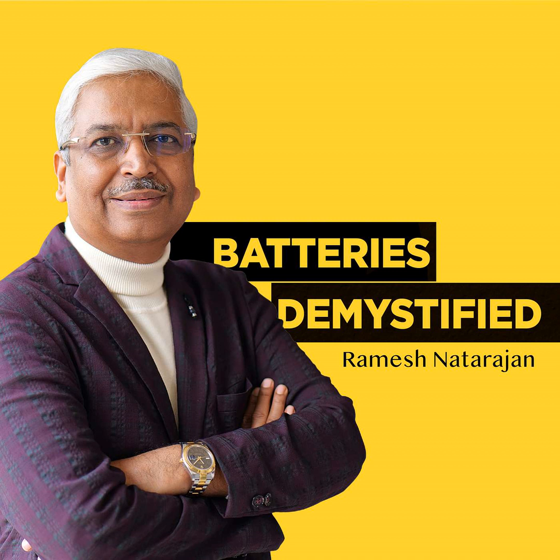Okay, but I don't think anybody mixes this with acid and puts it in any case. Sure. And from the battery point of view, I would like to know, is the miscibility almost similar with water? If you just dry mix this powder with your other additives, carbon and barium sulfate, and then mix it with lead, it will perform very well. You'll have no issues, no difficulties. If it can be dissolved in water first, that might be a little bit better. But to be honest, I don't anticipate they would see much difference.